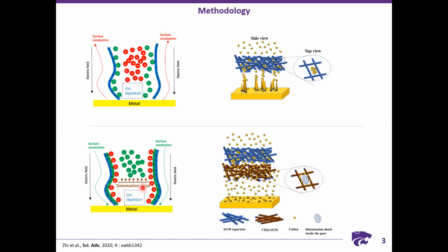Also, it will form a concentration gradient, unlike in diffusion where there will be a gradual concentration gradient. Here it can form a deionization shock. What it means is that the counter ions, that is the anions present in the solution, will get expelled, and there is a drastic change in the concentration. Here there will be a lot of anions, and just next to it there will be no more anions present. So it's just like a shock wave that can propagate in air or water, or any other medium. The difference in the concentration is quite huge, and these shock waves can propagate over time.